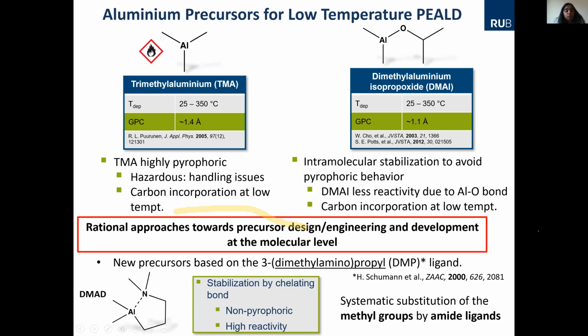So people have tried to modify the precursor. For example, here you see you have two methyl groups, like here you have three. So one of the methyl groups is replaced by an alkoxide group, that's an oxygen coordinated ligand. And in this case, you sort of reduce the reactivity. On the other hand, this is good because it's not so pyrophoric, but still carbon incorporation has been an issue. So you have made some compromise on the reactivity. On the other hand, it still works as a good ALD precursor.